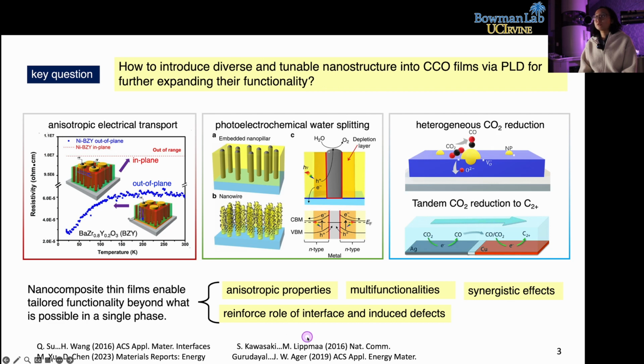Also, Professor Lippmaa's group developed the vertically aligned nanostructure for the water splitting catalyst. They introduced a metal nanorod into the oxide thin film. At the interface, they built a heterointerface to facilitate splitting the photogenerated electrons and holes to improve the efficiency of catalysts. Besides, a lot of researchers also work on using nanocomposites for catalysis, for example, carbon dioxide reduction. Each component plays a role in the catalytic process to achieve synergistic catalysis or even tandem catalysis.